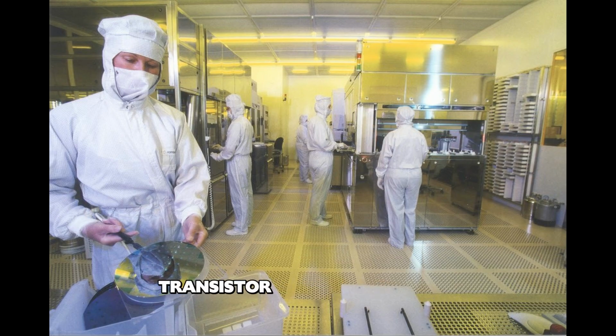The first silicon transistor emerged from Bell Labs in 1954, and it took Morris Tanenbaum 6 months of failed attempts to produce it. The process began with growing a silicon crystal from molten material heated to 2,600 degrees Fahrenheit in a quartz crucible. Tannenbaum would lower a seed crystal into the melt and slowly pull it upward, rotating it at precise speeds while maintaining temperature uniformity across the entire furnace. A single temperature fluctuation would introduce crystal defects that propagated through the entire ingot, rendering it useless.